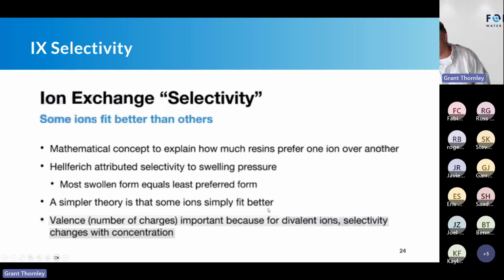When we take a look at DLE materials, not only do I want the lithium, but I have sodium, potassium, calcium. Those ions have a tendency to fit well into the same lithium slot on the bead. Others can't. So the valence number or the charge is important for divalent ions versus monovalent ions on selectivity.